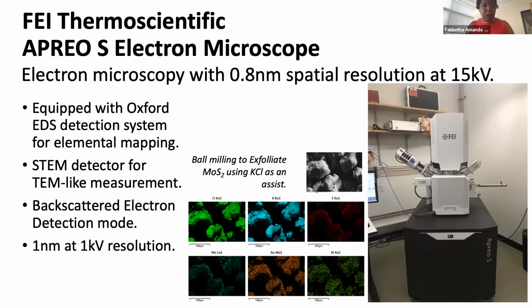in microscopy, we have been fortunate to be able to have some very advanced instruments. These are through National Science Foundation research grant awards. And so about 2 to 3 years ago, we installed the newest electron microscope by FEI Thermo Scientific, and it's equipped with an energy dispersive spectroscopy detector. Now in ideal cases, you can get around 0.8 nanometer spatial resolution. But the very interesting thing here is that with the Oxford detector system, we can also do chemical analysis.